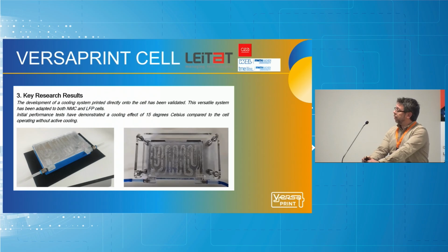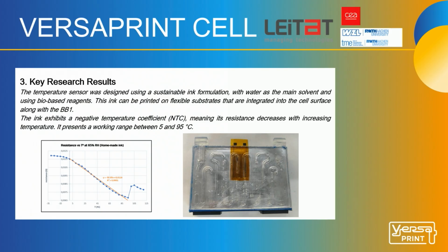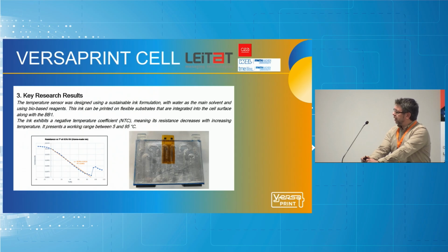Now, as for the results observed in the development, this cooling system was validated. We can obtain these circuits that can be adapted also for different types of cells, such as NMC and LFP. The initial performance test demonstrated a cooling effect of 15 degrees compared to cells operating without this active cooling. We printed several of these cells to be validated in the model systems with the different end users. For the temperature sensor, it was designed using this sustainable ink, with water as the main solvent, and using bio-based reagents. This ink can be printed on these flexible substrates, and it can be integrated along with the BB1, for a complete thermal management of this cell.